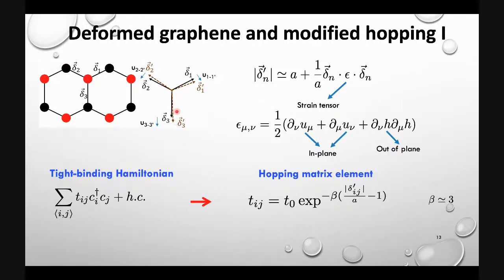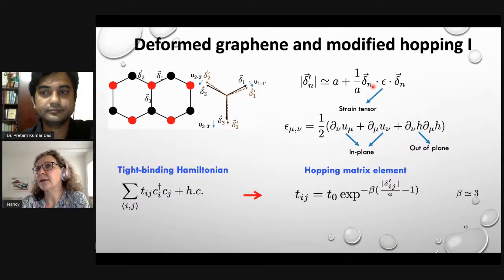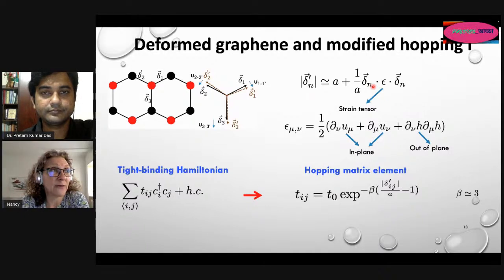So in general, the nearest neighbors to a given atom in the lattice will now be at a distance given by the modulus of this vector, which is the original distance plus a new term. And this term is described in terms of the strain tensor. When we deform a material, we describe the deformation in terms of the new positions of, in the case of a crystal, the atoms in the crystal. In the case of a continuum material, the new positions of the different points in the material.